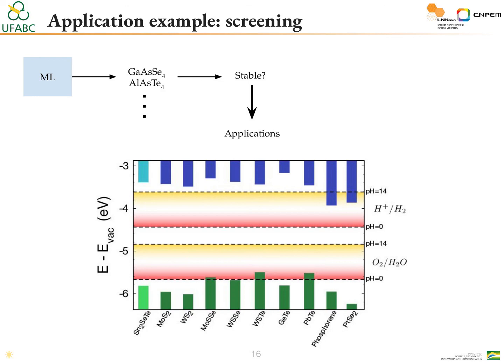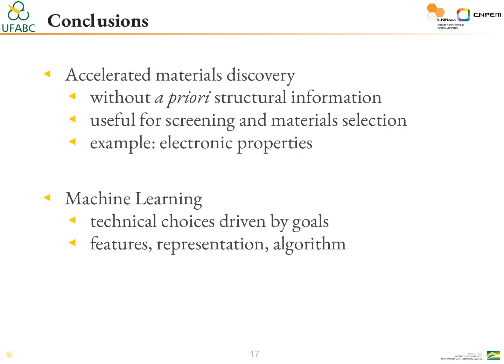In practice, our model can be used as the first step in a screening strategy for different properties. As proof of concept, we calculated with DFT the electronic properties of selected stable materials and identified novel potential candidates for photoelectrocatalytic water splitting. To conclude, we presented a machine learning accelerated materials discovery approach that is efficient even though